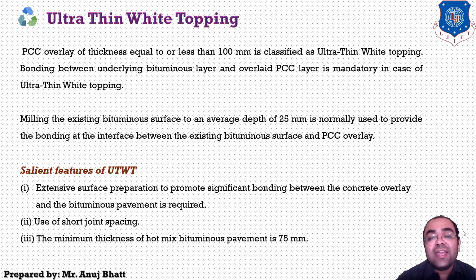Such bonding can be provided by some other method also, but milling is considered desirable because an effective bond between the existing and the overlaid surface is absolutely essential for better performance of ultra thin white topping. Fibers and high strength concrete are normally provided. Joints are spaced closely at an interval of 0.6 to 1.25 meter.